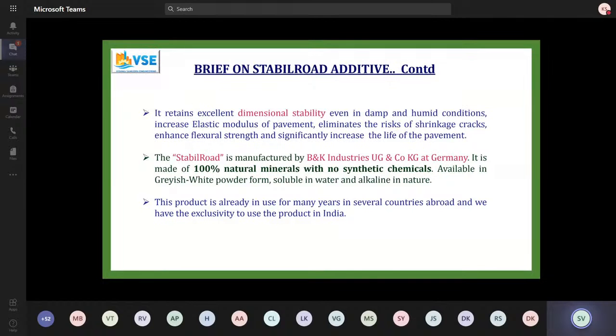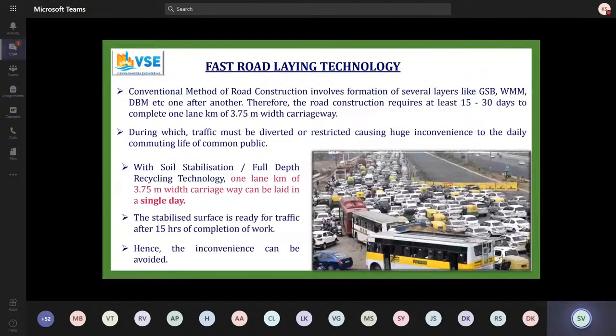One major advantage is a very fast laying technology. Typically, the conventional method or a cement road takes anywhere between 2 to 4 weeks to complete 1 lane kilometer, especially when it comes to cement. By using our technology, if everything is planned and logistics are good with cement, we can do almost 1 lane kilometer per day of stabilization. After 3 days, we can go for a layer of BT on top. So pretty much in 3 to 4 days, we are done with 1 lane kilometer. That's how fast we can do it.